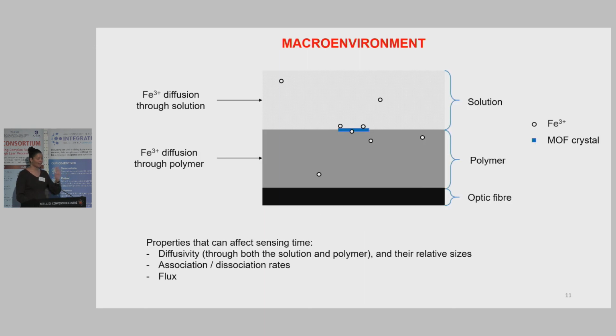This is a cross-section of the modeling environment. When we see the circles, it's iron 3, so we're looking at how iron 3 diffuses through solution, the polymer, and at the bottom we have an optic fiber. There are MOF crystals distributed throughout the polymer. However, we first consider a crystal at the solution polymer boundary. And then we can study for properties that can affect sensing time.